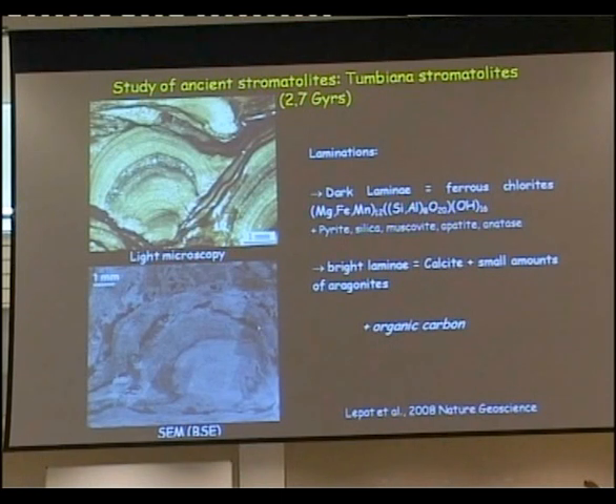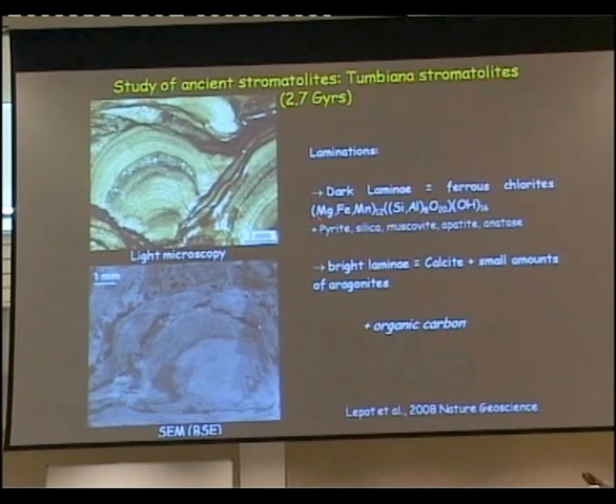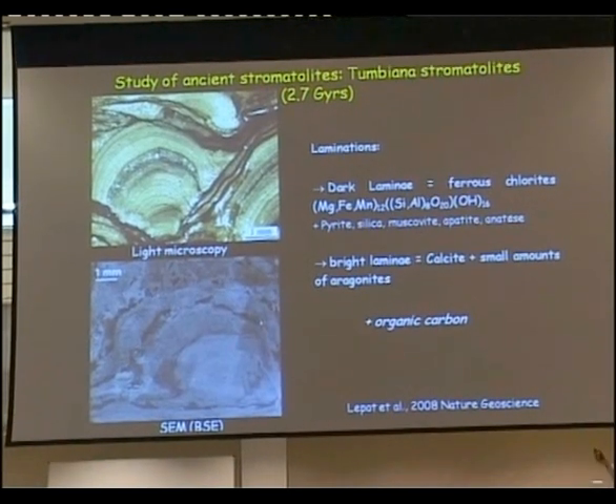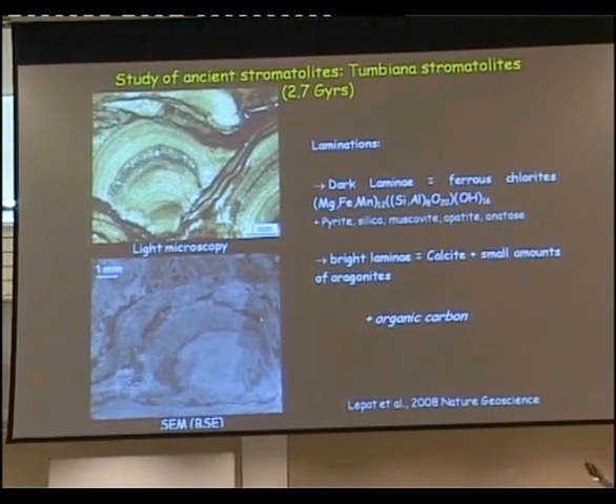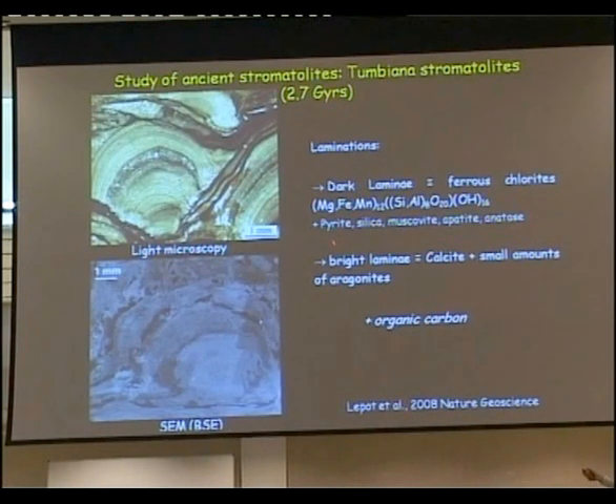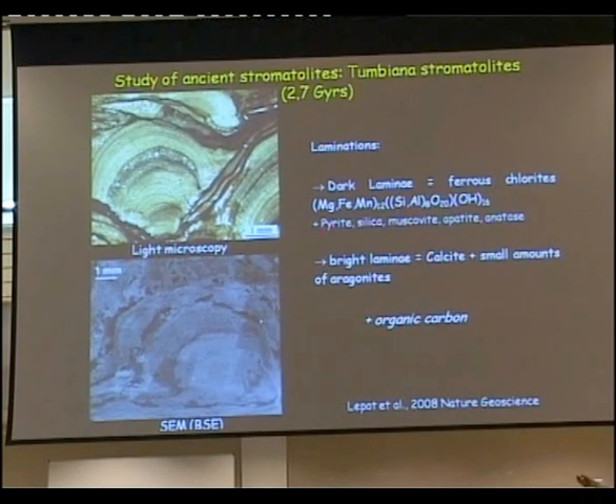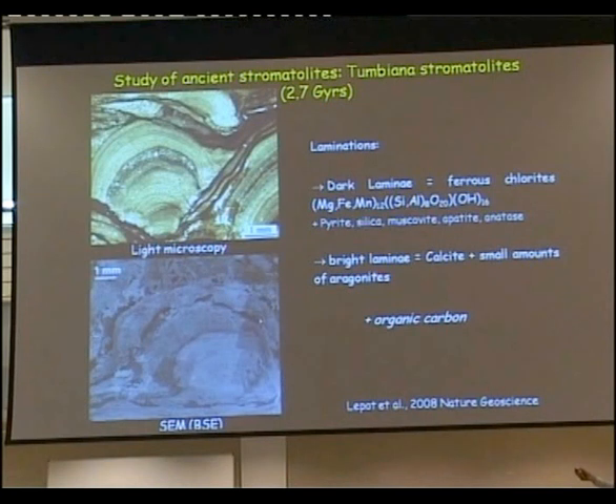So you see, these are reduced elements, plus pyrite, silica, and other accessory minerals. So that's the dark laminae. The bright laminae, they are made of calcite plus small amounts of aragonite that seems to survive the aging. And there is some organic carbon everywhere, both in the bright laminae and in the dark laminae.